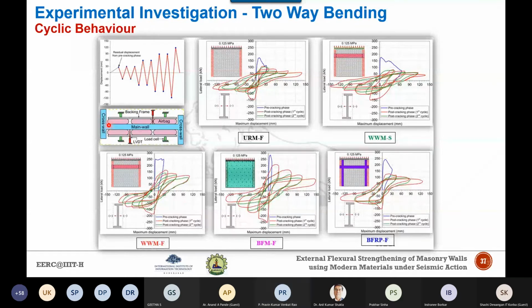Here you can see that the load has been applied to the wall in 2 phases. One is called the pre-cracking phase, which consists of the first half cycle of the load up to significant cracking of the wall, that is, up to a well-defined collapse mechanism. And second is the post-cracking phase, which consists of a reversed cyclic load with the displacement loading history.